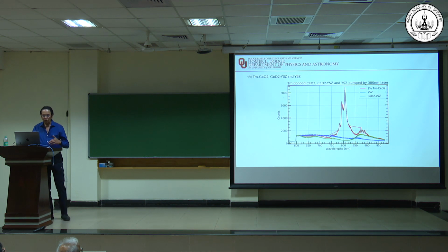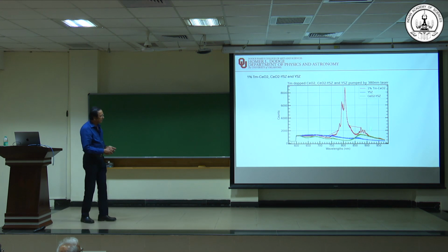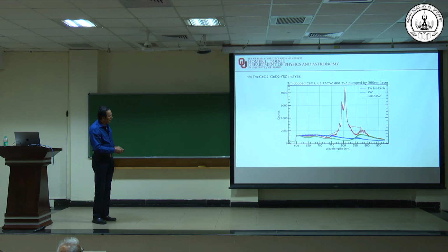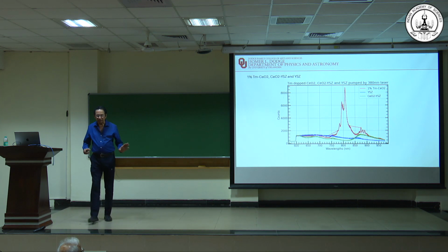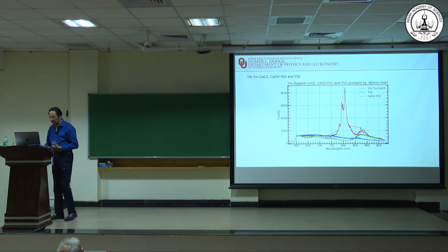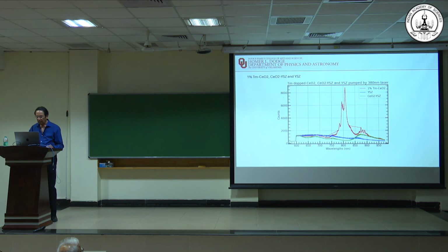And these are the photons produced by thulium atoms. So these are basically thulium atom photoluminescence from the cerium oxide films which are doped with thulium. And now we're going to create some nitrogen oxygen vacancies in this and see if they form some kind of a color center with these states, right? So that's the next part of the study, right? So we are working on that.